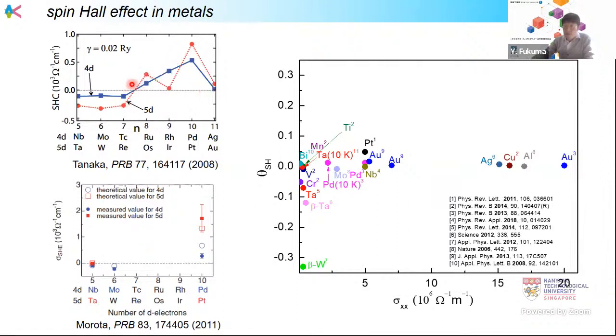This kind of theoretical work is also recapped by the experimental work. Now we can see the spin Hall effect in many different pure materials. What we can see here is, for example, beta tantalum and beta tungsten show a larger conversion efficiency, but this beta phase is a non-equilibrium state. That's why we can see it only in a very thin layer. That's why for the bulk material, we can say the conversion efficiency is not too high. It's less than 10%.